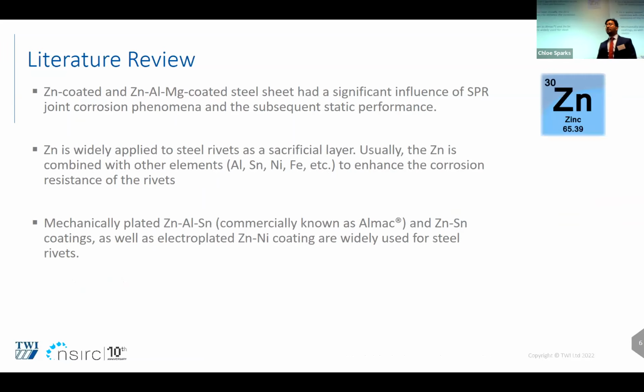So when we are doing this joint, galvanic coupling is occurring. Galvanic couples tend to form here, and to protect against this, a few coatings have already been used on rivets. These coatings are zinc-based coatings, zinc, aluminum, magnesium-based coatings, and they are widely used as a sacrificial layer on the steel surface until now.